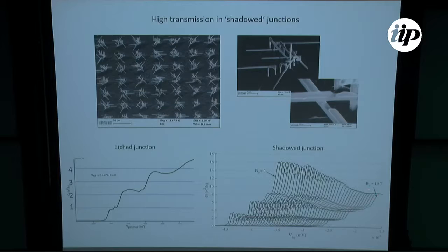And then as we go up in field, this is a lot of different traces as we go up in field here. It splits this degeneracy and really goes into 2e, at least for some levels. Yeah, it's a Delft geometry, the old fashioned one, where you use this junction here. This is only on one facet, so these are kinked nanowires in a different orientation. And then it's only on the top facet of the wire, but then it's in situ. You don't need to etch this way because it's already formed in situ. So you just have a native junction in the wire.